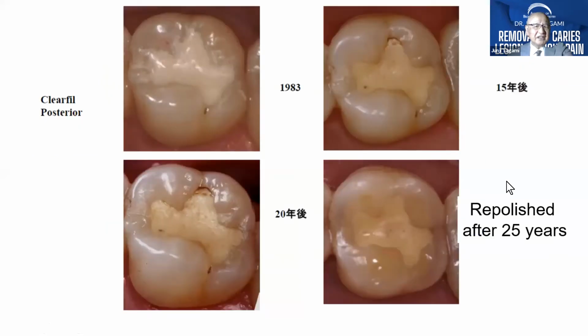This is his very old restoration placed with the chemical cure type of adhesive and composite. And you can see that this is the class 1 composite resin restoration placed in 1983. And after 15 years, you can see some porosity at the surface of the restoration because the composite resin was mixed together. And also slight marginal discoloration can be seen. But these changes were not so significant in the clinical situation. And after 20 years, almost the same.